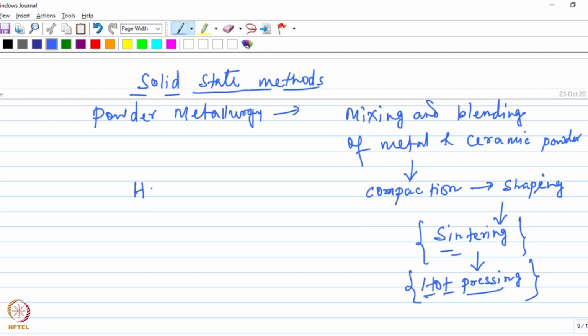You may also have processes such as hot isostatic pressing for better densification. In short, this is known as HIP. Hipping is a very effective technique of making composite materials into full density, because conventional compaction and sintering may not be able to close all the pores and it might leave behind porosity, and the other problem could be the clustering of the particles, right? But hot isostatic pressing applies the pressure from all directions uniformly, and therefore the packing is more uniform, and as a result of that the densification is better. Okay, and you would get a better density, a higher density at the end of the sintering process.